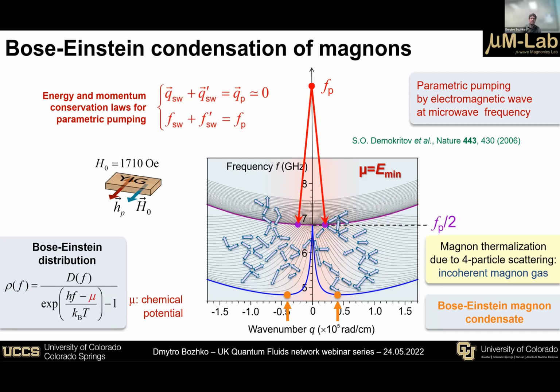Yeah, it becomes strong at higher frequencies because of the quadratic spectrum. You have an increase in the group velocity with frequency, and that basically brings the velocity close to and higher than the velocity of the phonons in the spectrum. And there are tons of phonons at those high energies, so there are lots of possibilities to scatter.